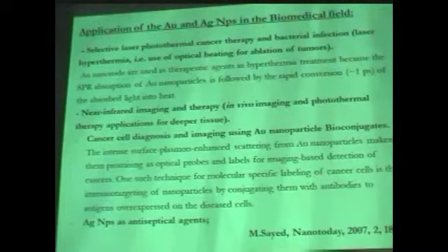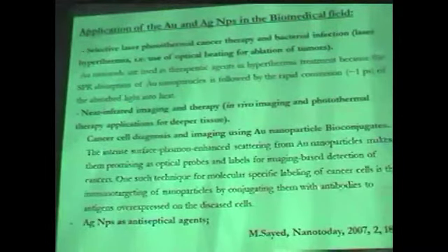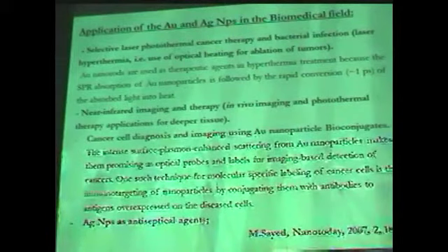The laser hyperthermia means the use of optical heating for ablation of tumor. The gold nanorods are used as therapeutic adjunct in hyperthermia treatment because the surface plasmon resonance absorption of gold nanoparticles is followed by the rapid conversion, around 1 picosecond, of the absorbed light into heat. So we can heat with the gold nanoparticles.